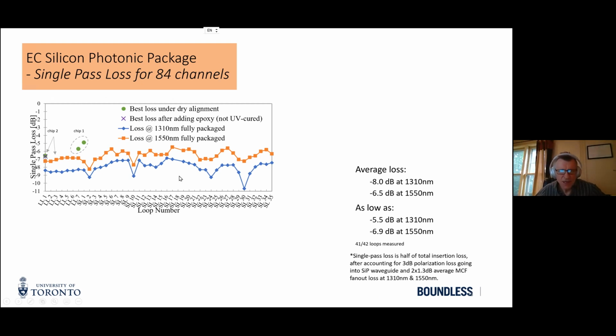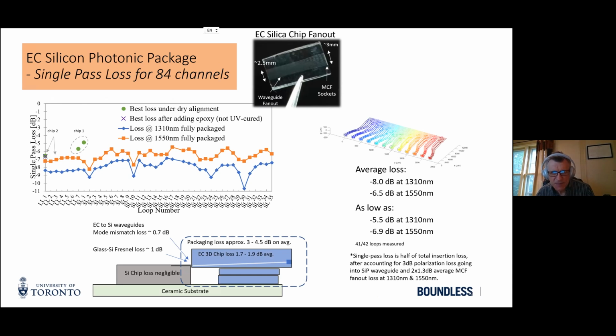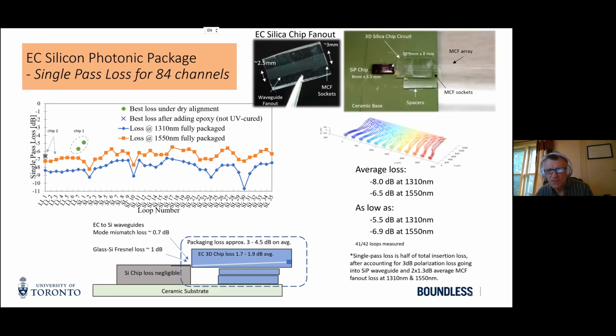So in the end, we could find additional losses due to the silicon chip, the mode mismatch, et cetera. And over 84 channels, we have losses around 7 or 8 dB. We basically are new to this packaging game, and we lost about 3 dB due to packaging losses. This is the creep of the epoxy as we're aligning, but that of course can improve. And so I think this is really a sound technology for edge coupling, and there is a picture of the device.